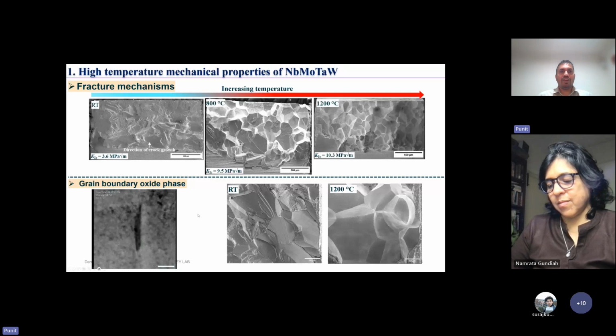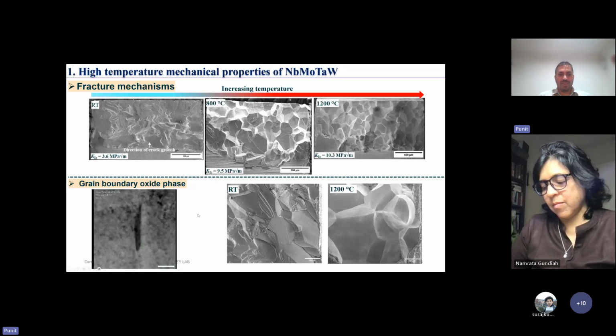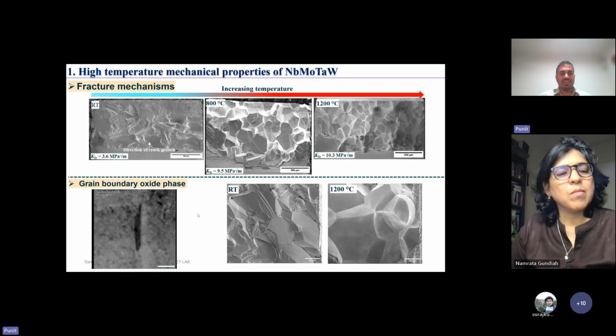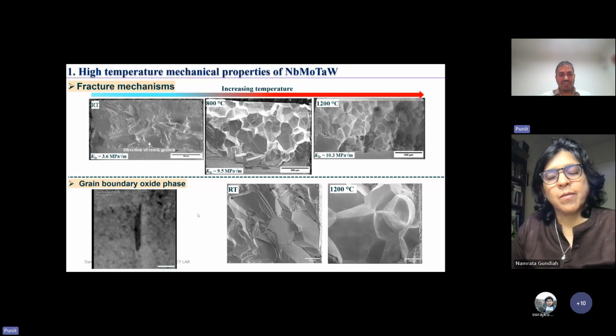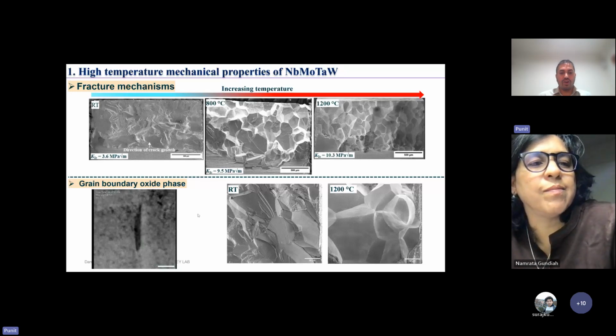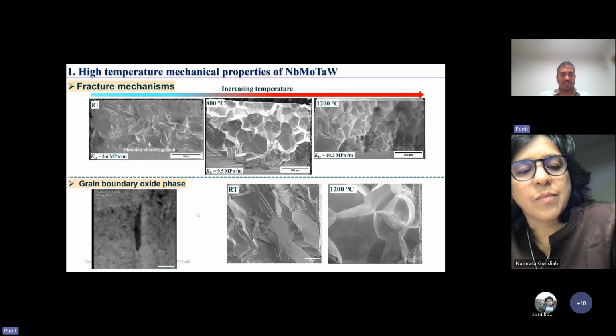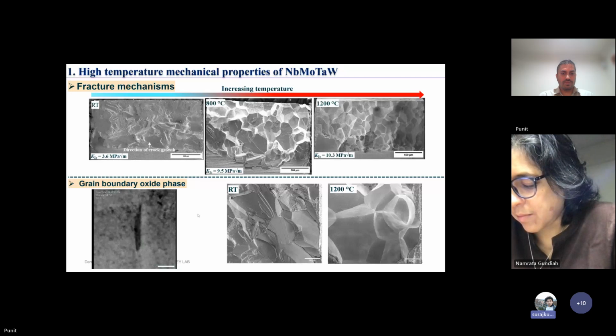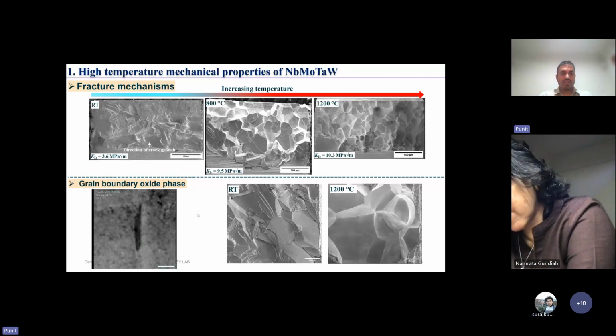Okay. So we were measuring the strain using the extensometer. We had a high temperature extensometer which goes inside the furnace, with long ceramic prongs. But because the material fractured in the yield region, we were not able to get really significant data out of that extensometer. So we just used the load line displacement for those strain values, but we corrected it to the elastic modulus of the material that we measured using an ultrasonic method. We have small probes that you can put on the samples and measure their elastic modulus. And if I'm correct, you are doing all these experiments in an inert or vacuum environment, right? Yes, we are doing these tests under an argon environment.